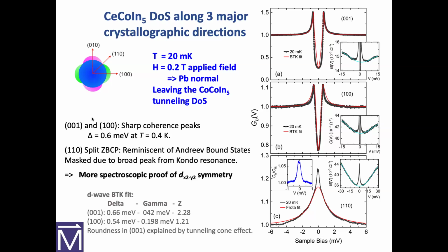The Cooper pairs go, that's a very, very strong Andreev reflection, I'm going to break pairs. So in the high TC superconductors, if you tunnel into the 110 direction, you have quasi-particles along the surface. And you measure that within the superconducting gap as a peak in the density of states at zero bias.